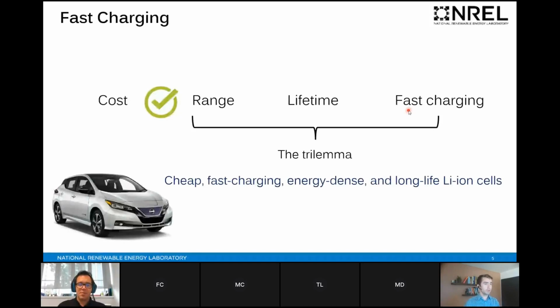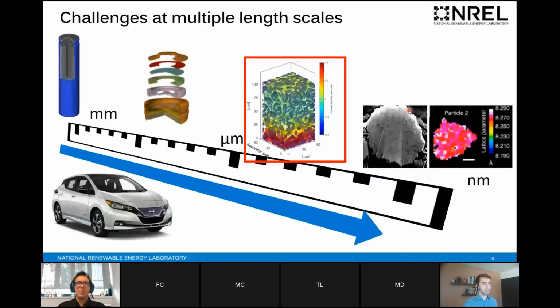So we want to understand firstly the cause of limitations of fast charging, and we've got research at NREL that bridges multiple length scales from millimeters to nanometers. But in this talk, I'm just going to focus on the electrode scale and talk about the limitations at the electrode scale. So in a lithium-ion battery, the main limiting factor is on the graphite electrode. So during charging, we delithiate the metal oxide cathode and lithiate the graphite anode. And unfortunately, graphite has its potential versus lithium of about 0.1 volt when it's in a pure graphite form. And this means that we only have a luxury of about 0.1 volt overpotential to apply to lithiate the graphite before the potential versus lithium on the graphite side decreases to below 0.